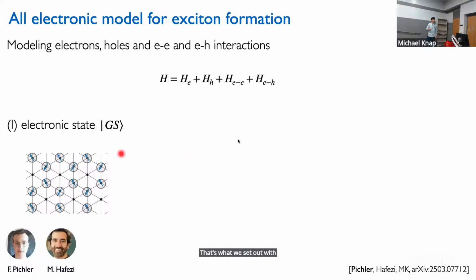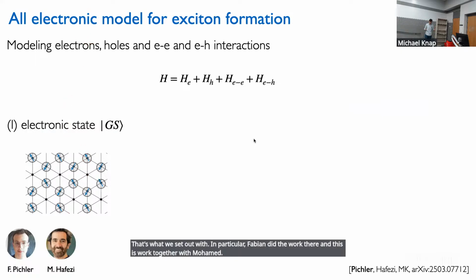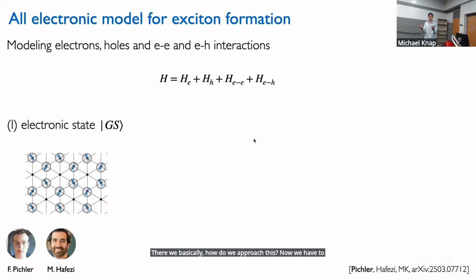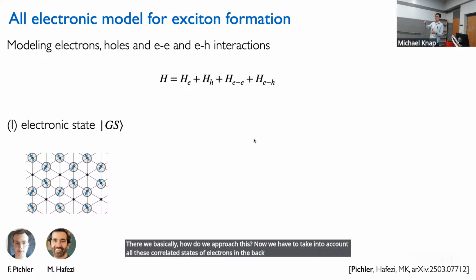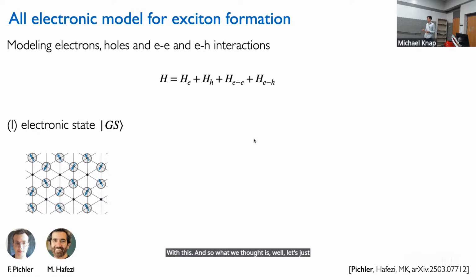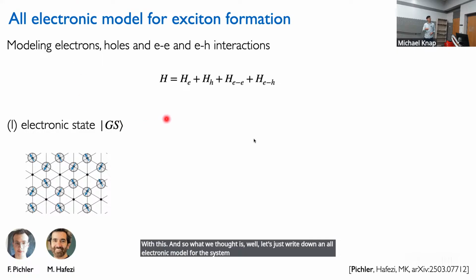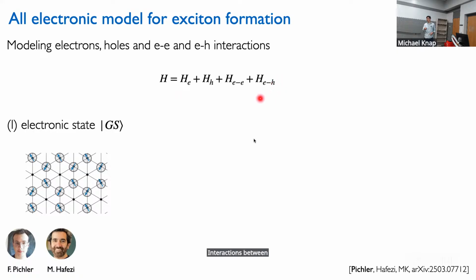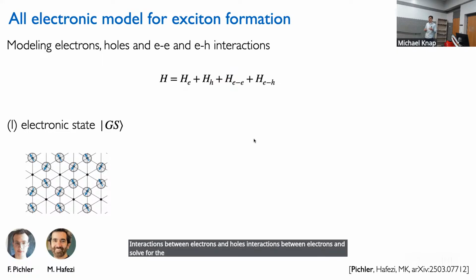In particular, Fabian did the work there, and this is work together with Mohammed. How do we approach this? We have to take into account all these correlated states of electrons in the back. And the exciton itself is not really point-like anymore, at least in these cartoon pictures, because the exciton can be either non-monogamous, distributed over the sample, or it can be a point-like particle. So how do we deal with this? What we thought is, let's just write down an all-electronic model for the system, where we write down an effective Hamiltonian for electrons, for holes, interactions between electrons and holes, interactions between electrons, and solve for the exciton structure in this model.